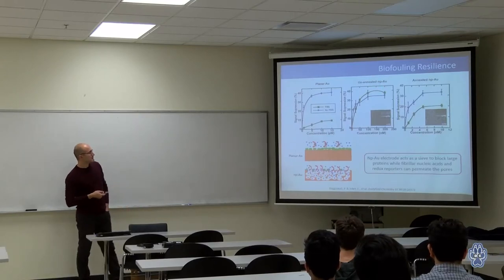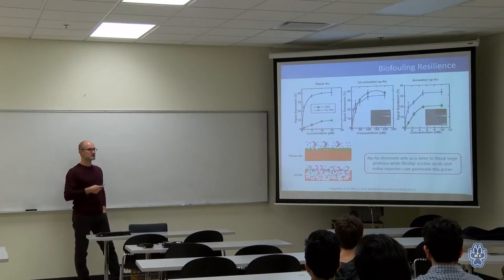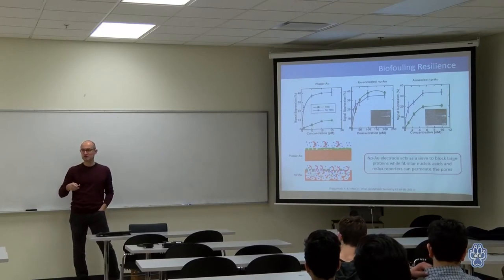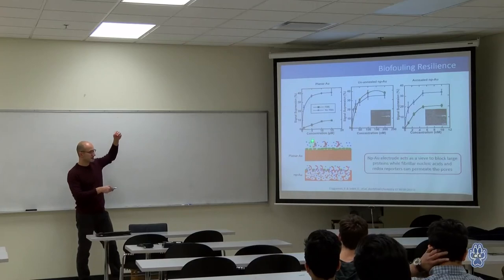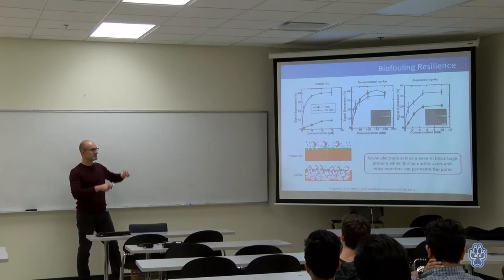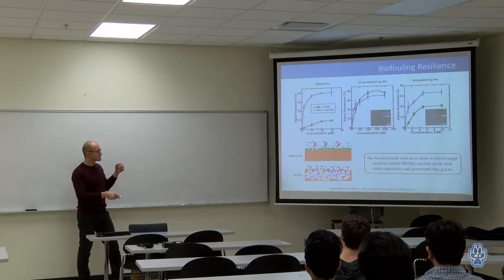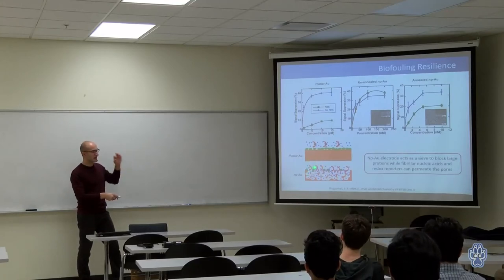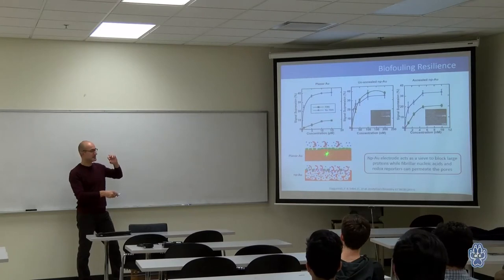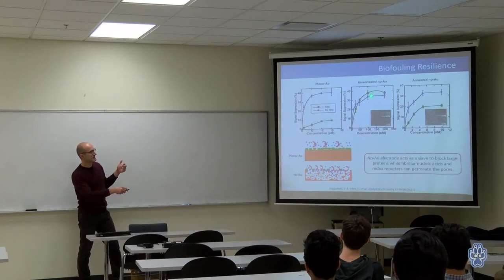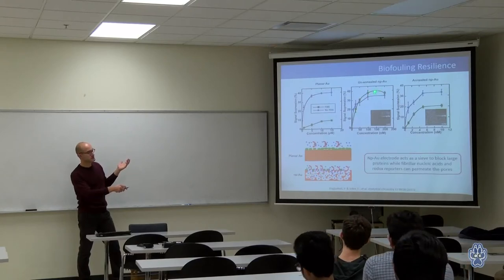What we hypothesized is that the porous electrode acts like an intrinsic sieve. Those large proteins or cells get stuck on the top surface, but they don't block it because the pores are not perfectly circular. So those small redox molecules and the fibrillary, hair-like DNA can actually seep through the pores, which are not inhibited by the proteins. And you can get a comparable signal in serum or no serum.